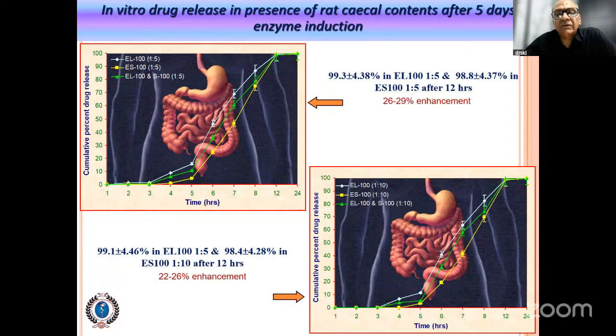Enzyme induction, again, will give a higher concentration of the enzymes. So that cecal content was added into the dissolution medium with simulated colonic fluid and we performed the dissolution studies. We found a 26 to 29% enhancement in drug release if the enzyme is induced after 5 days of feeding of the chitosan.